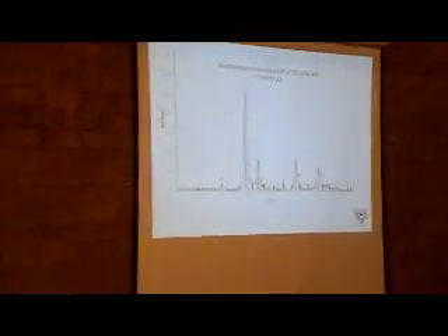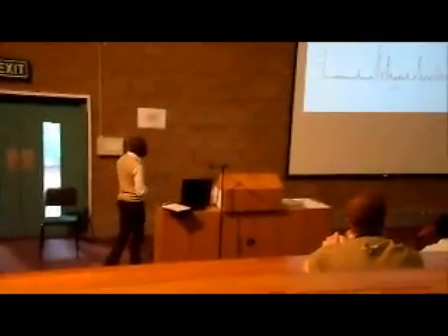And we can see that this is still pretty much constant over there. So this peak over here at 15 is slightly more intense in the rehydrated compared to the original spectrum. But one thing which was of great interest to us was that upon complete thermal decomposition, or thermal heating to the oxide form, we obtained this very clean image over here. Now this image matches perfectly with literature, so we can confirm that it actually did produce erbium oxide. And this image was taken from a database, which was used as a reference.